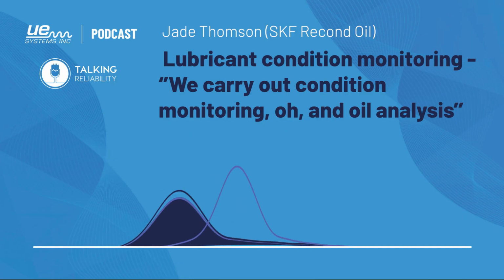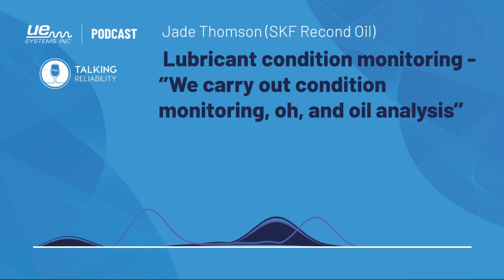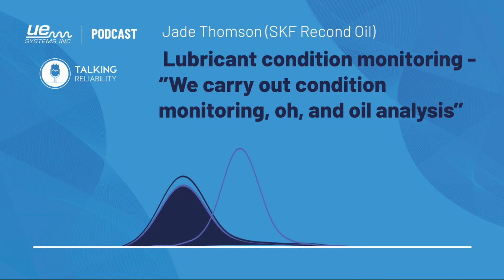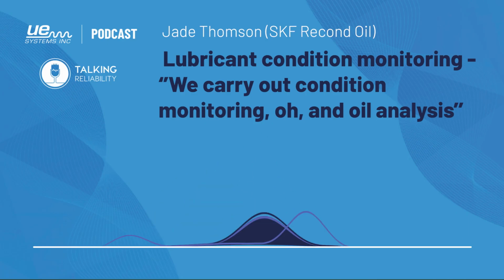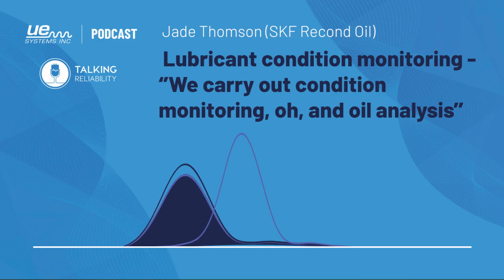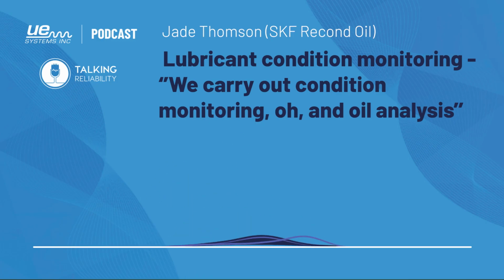So we've got an example here of routine oil condition monitoring. This was a user that does really, really frequent analysis. It's a public sector customer, so it was a safety reason they were doing this analysis. And we monitor all the wear, contamination and chemistry parameters for these lubricants. And all of a sudden one day we see a massive increase, as you can see on the top graph, in phosphorus, shortly followed by copper.